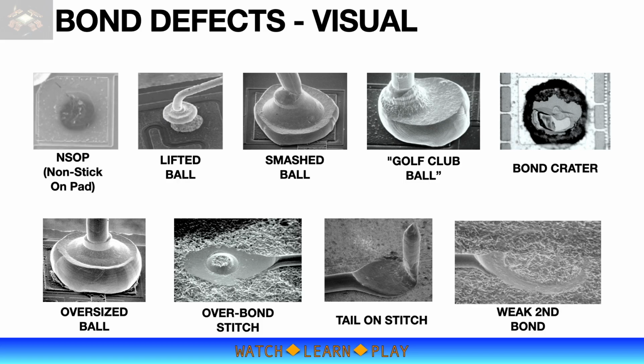Oversized ball is simply due to the FAB being too big. Reducing the FAB size will correct the problem. Overbond stitch is due to bond parameters being too high, particularly the bond force. Reducing the bond force will likely correct the problem. Optimizing capillary design may also help address the issue. Particularly, a larger base angle will improve the shape of the stitch and may allow higher bond parameters without overbonding.